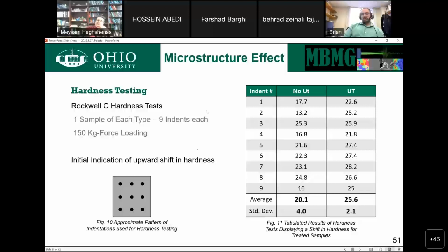So what are the effects that we see? Well, in our case, we focused on hardness tests because we're printing Inconel 718, which is highly expensive. And so to get an idea of property shifts, we're focusing on the hardness and going into small scale testing so that we can get properties without having to use a large amount of powder. And what we see is an average hardness increase of about 5 points on the Rockwell C scale and a tightening of the standard deviation. So not only is the hardness going up, but the variation in hardness across the sample goes down, which is a nice benefit that we can get.